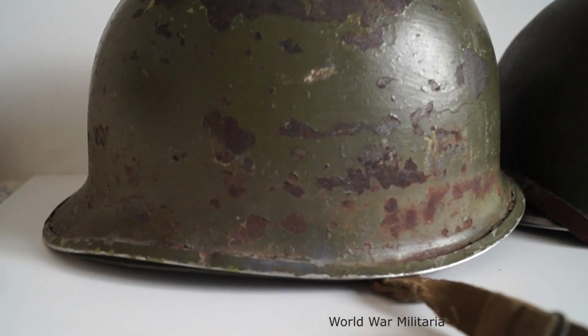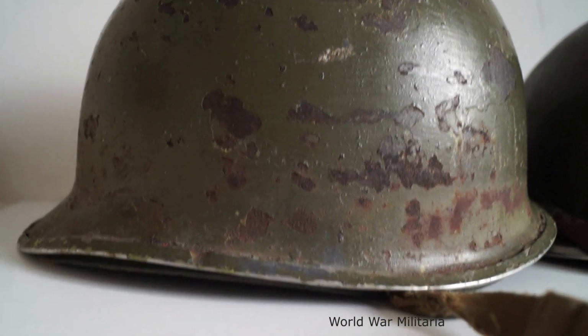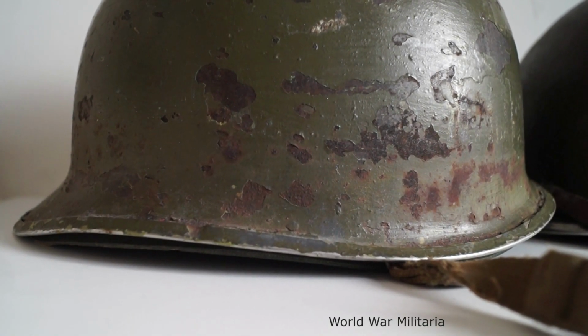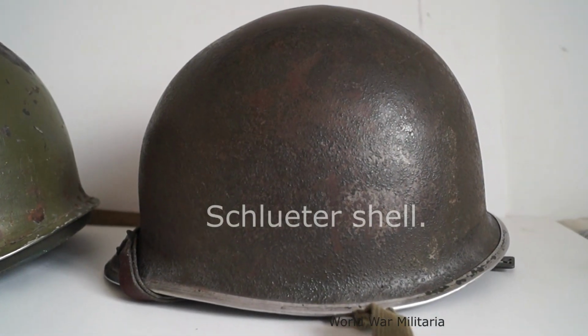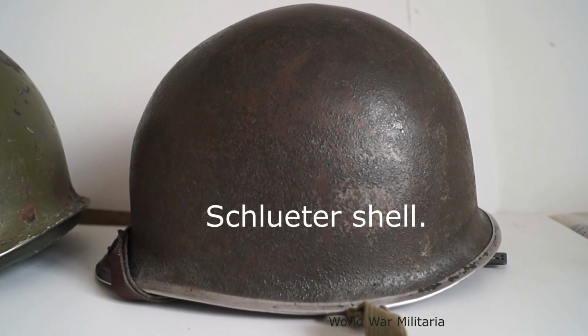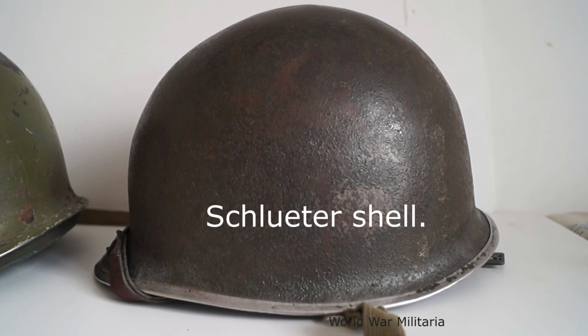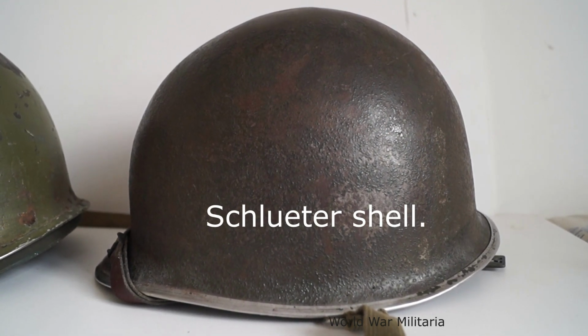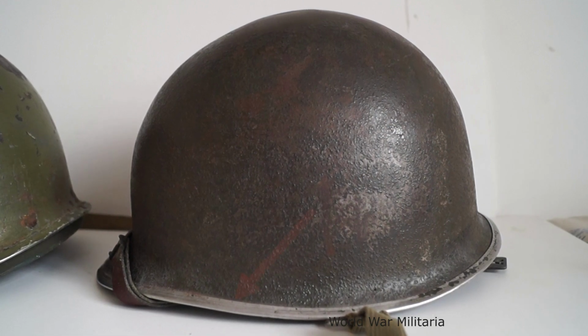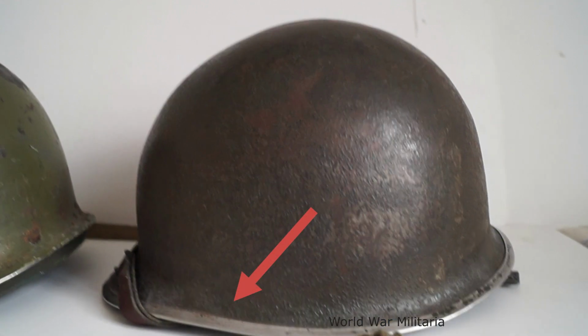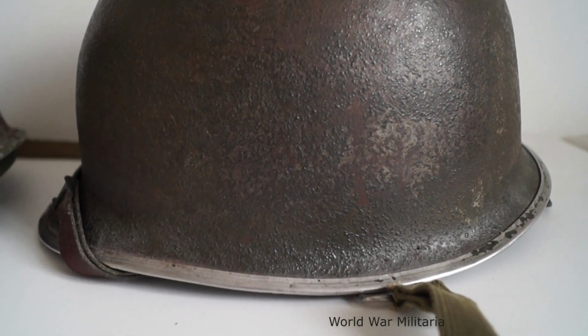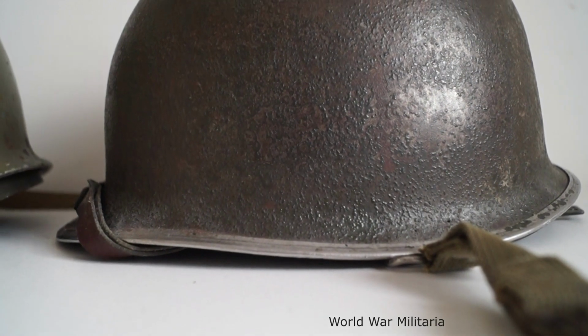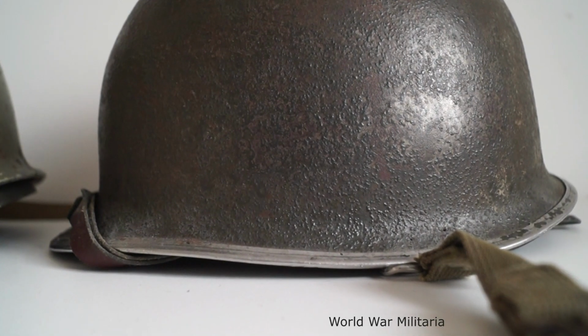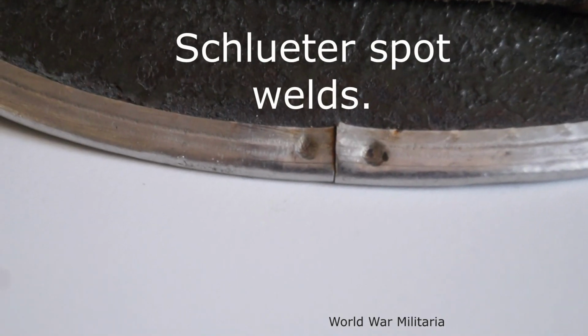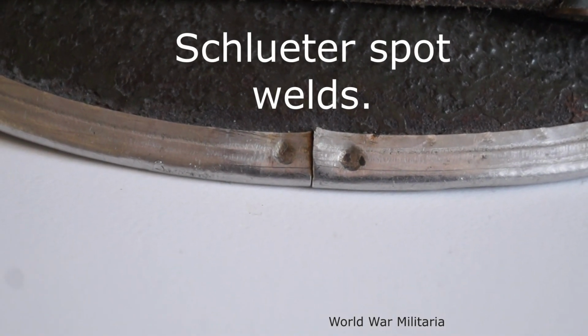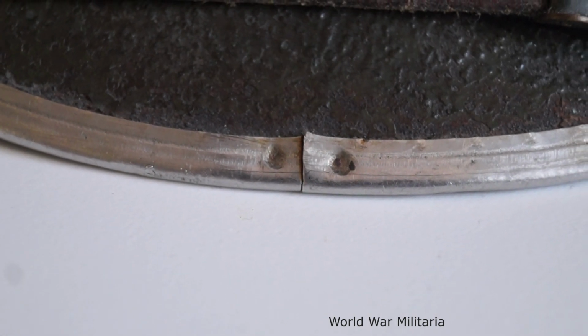The spot welds to attach the rim are round, whereas McCord shells are oval. The chin strap loops on Schlueter shells have somewhat rounded corners, with the ends bent slightly outwards. The chin strap loops on McCord shells have square shaped corners. The steel sheet lot number under the visor of the Schlueter shell has a larger figure plus an S towards the rim. Some Schlueter shells have the steel sheet lot number above a chin strap loop, others have no stamp at all. McCord steel shells are stamped under the visor with some variation in placement.